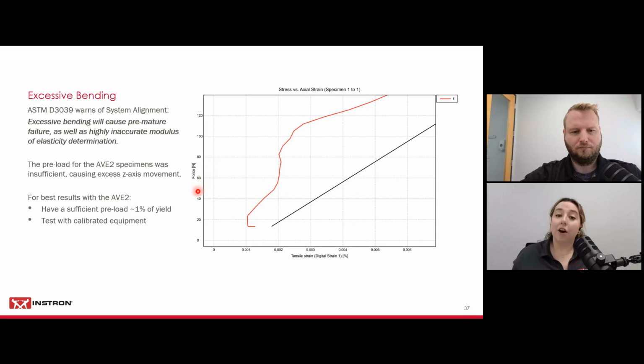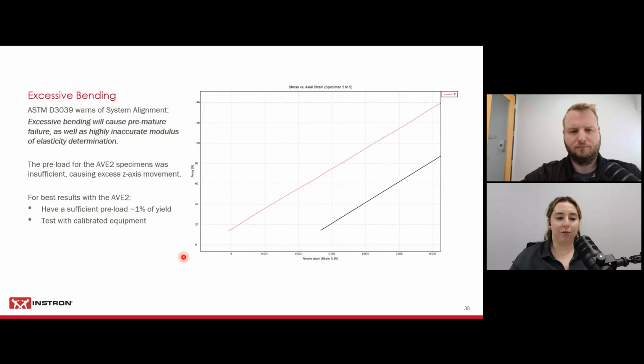and that would have helped with removing my slack. And also we want to make sure we're testing with calibrated equipment. We're not testing with equipment that's been verified by a field service engineer, but you do want to make sure that your lab is staying up to date on your calibrations and certifications. And if we click one more time, we'll see a comparison of the clip-on. Because the clip-on is actually making contact with our specimen, it does not have that z-axis error, but you still absolutely want to make sure that you have that sufficient preload of around 1% of yield and that you're testing calibrated equipment so your lab is having the best chance to capture the best data.